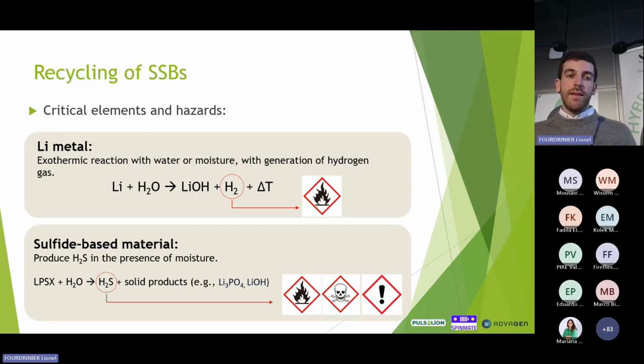And if it's concentrated and you have some temperature, it can react with the oxygen from the air, and you can have a fire or an explosion. So if you are dealing with huge amounts of lithium metal, you have to take this into account. And the other material is the sulfide-based material, in case you have a sulfide-based electrolyte. The sulfide electrolyte also reacts with water, producing the hydrogen sulfide. And the hydrogen sulfide is a very toxic compound.